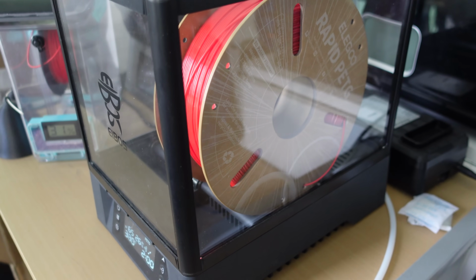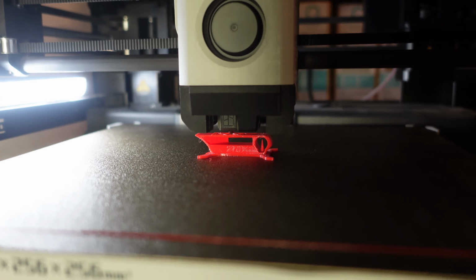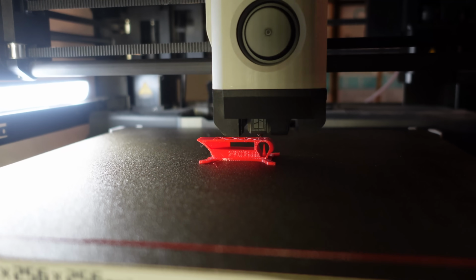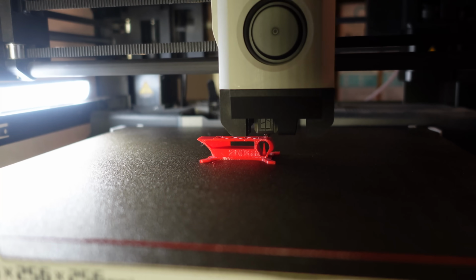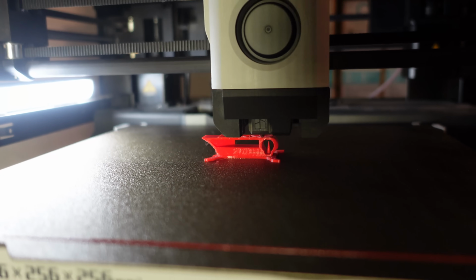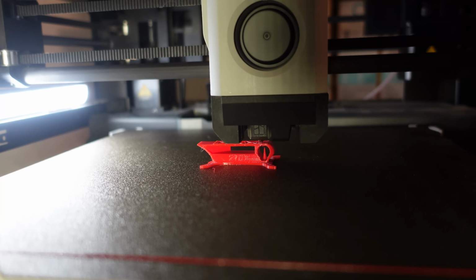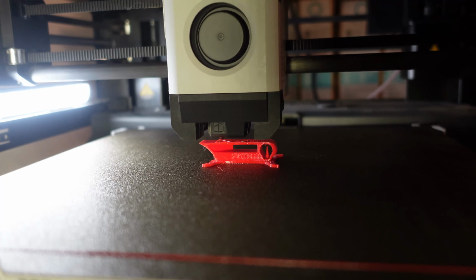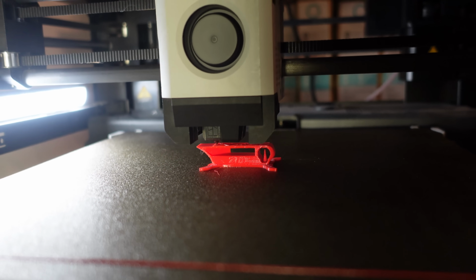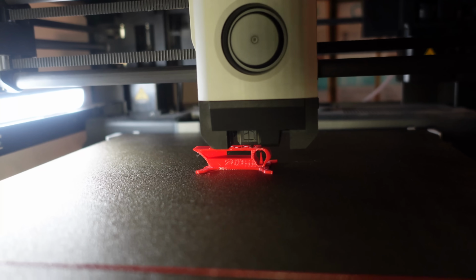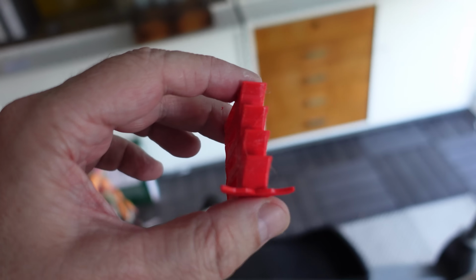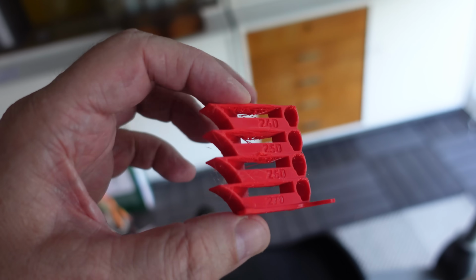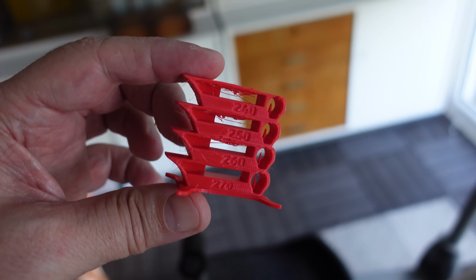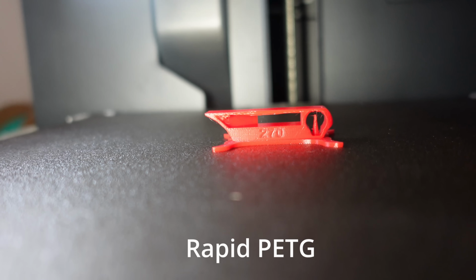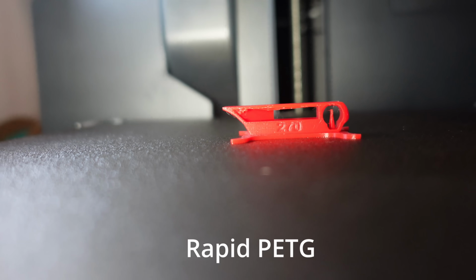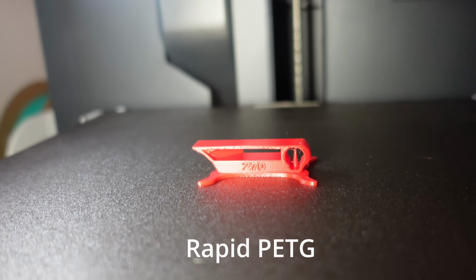And in the meantime I am printing the tower with the PETG Pro using the same G-code, even if it is above the recommended print temperature range. And as I predicted, this one is less sensitive to moisture, so it looks okay even on 270 degrees Celsius. But the test objects I will print on 260, which is the maximum recommended print temperature. And again, those overhangs look nice, only I'm not too happy with this bridging, so this filament goes to the filament dryer too. Printing finished a few seconds ago, and perfect printing, 270 degrees Celsius.